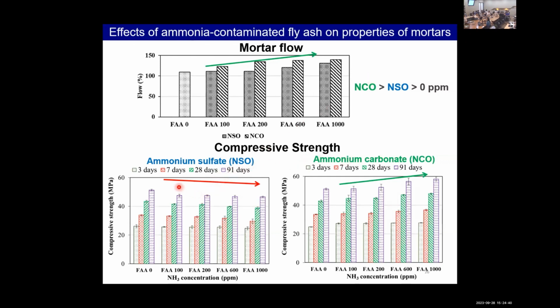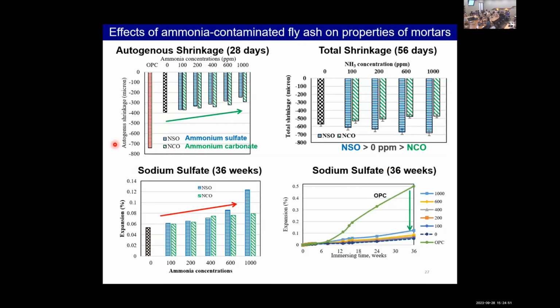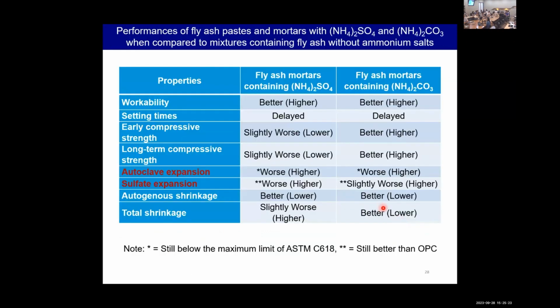For compressive strength, it decreases with ammonium sulfate fly ash, but for the ammonium carbonate one, compressive strength can be increased. And for autogenous shrinkage, it can be reduced. But for total shrinkage, ammonium sulfate increases total shrinkage, while ammonium carbonate decreases it. For sodium sulfate, compared with the non-ammonium fly ash, the ammonia-contaminated fly ash increases the expansion. But compared with OPC only, the value is much lower than OPC. This table shows the summary of the performance of the paste and mortar with the ammonia-contaminated fly ash compared with the non-ammonium one.